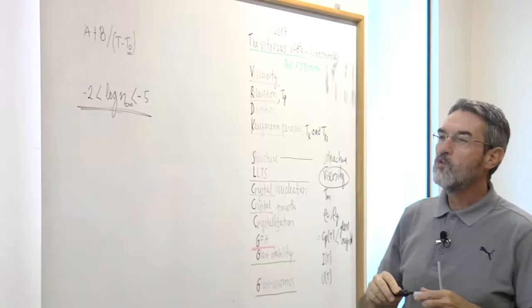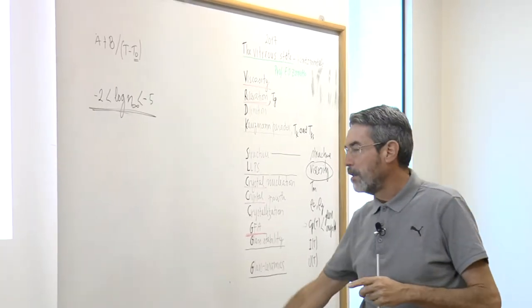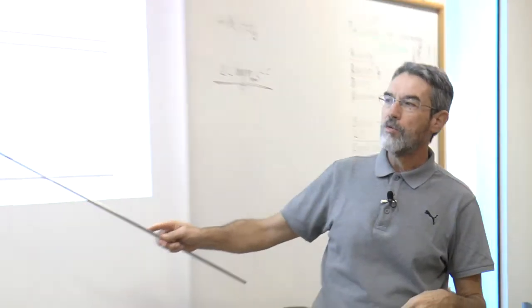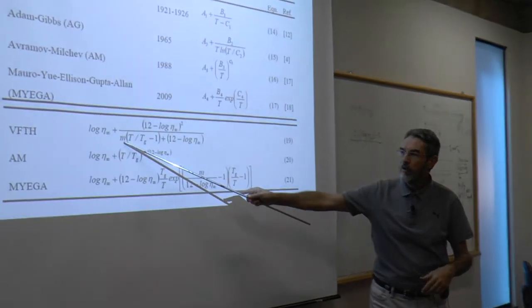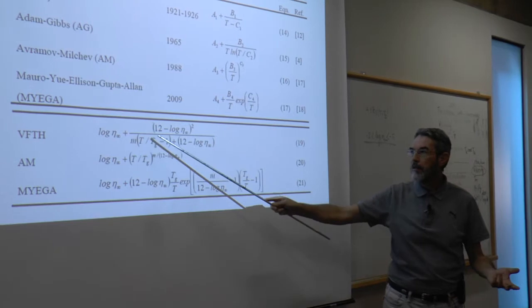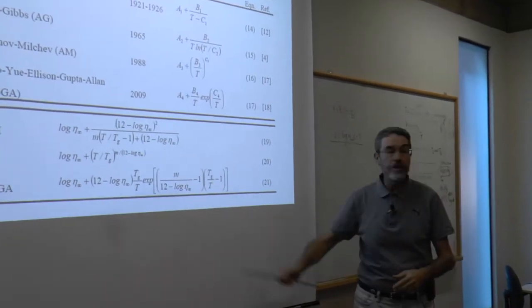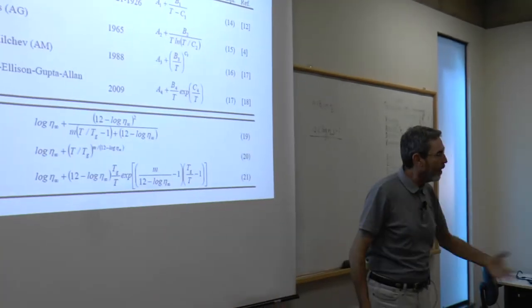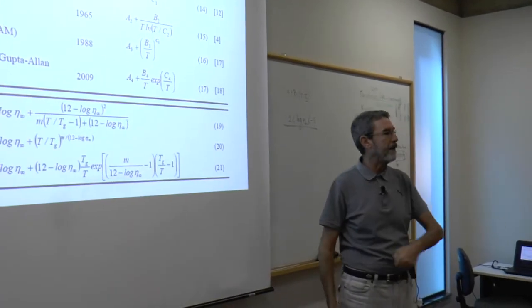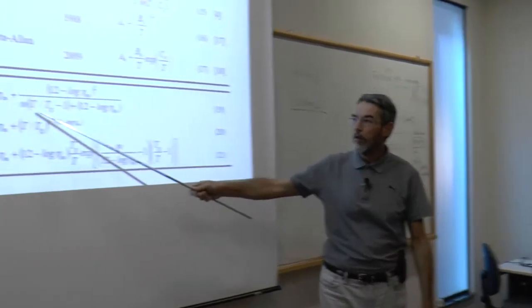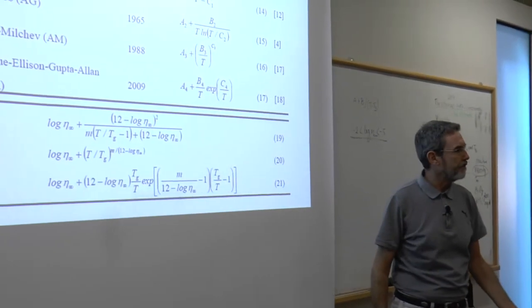So this is one parameter which you can take an average like -3 or so, or -3.5, and then you are left with only 2 fitting parameters, m and Tg. Of course, you can also measure Tg independently, and then you have Tg. If you can measure by DSC, for instance, so you're left with only one unknown parameter, m.